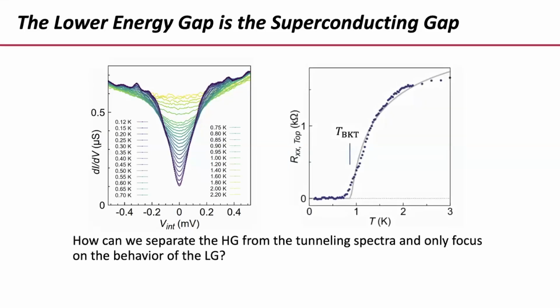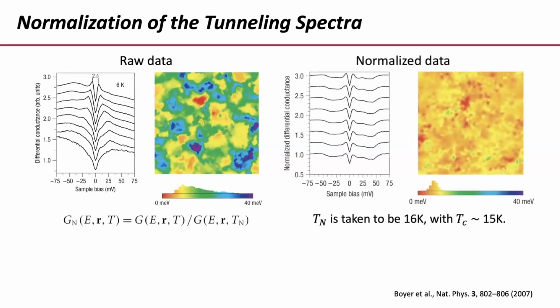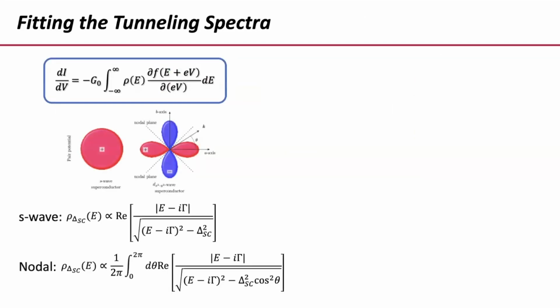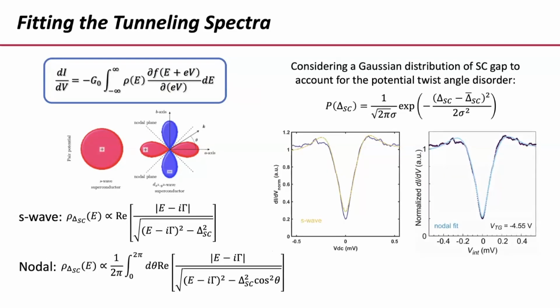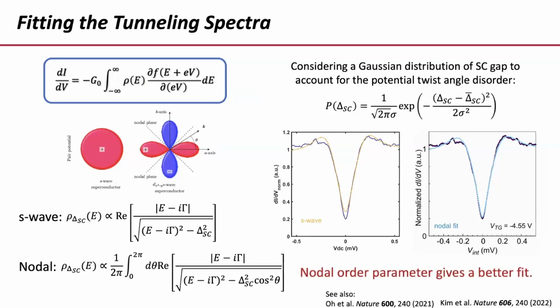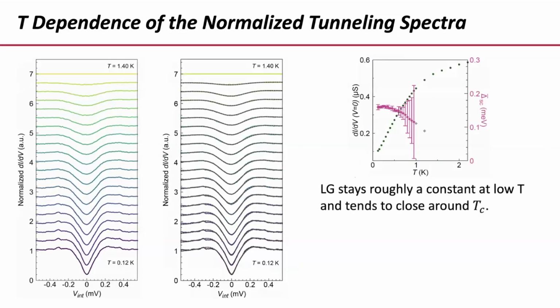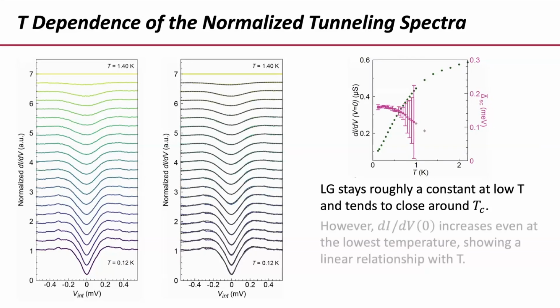So if you look in detail at the superconducting gap, which is the lower energy gap that you see in there, you can see that it starts to deviate very quickly. This gap fills very quickly, well before there is any deviation from zero resistance state, okay? You can analyze all of this by using the same procedure that was applied to cuprates, for example, okay? I'm sorry, I'm going a little bit fast through this, but you can fit this with various superconducting distributions, and it fits much better to a nodal than to an S-wave superconductor, okay? You can do the temperature dependence of this; this gap fills very quickly with temperature, which is consistent with what you expect for nodal behavior, where you immediately start exciting quasiparticles with temperature.